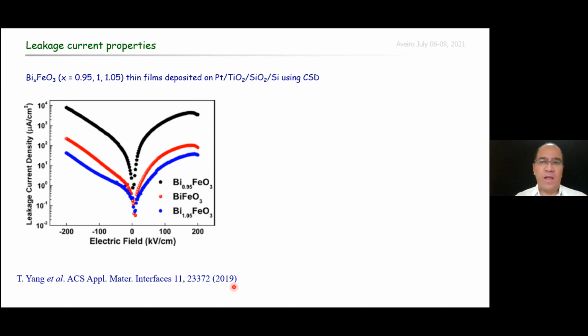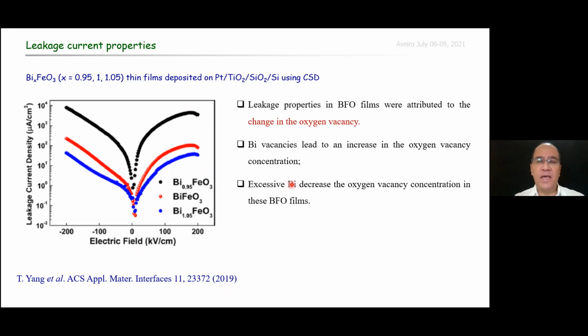Okay, in this case, the leakage properties were attributed to the change in the oxygen vacancies. Yang et al. concluded that bismuth vacancies increase the oxygen vacancy concentration, while bismuth in excess decreases the oxygen vacancy concentration in their BFO films. In other words, in their opinion, the oxygen vacancy concentration has a high impact on the leakage current of BFO films.